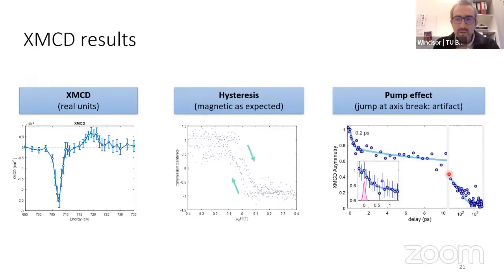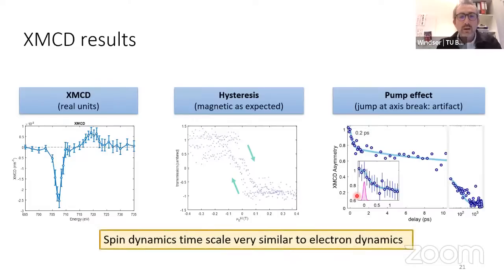I'm pointing this out because here there is a drop, and this drop here is artificial because in this part of the image, the resolution changes to be about 50 picoseconds because this is on much longer timescales. This is now in nanoseconds, hundreds of picoseconds, and this is in single picoseconds. And so we see that the initial drop here is on the order of 200 femtoseconds, which is very similar to what we saw in the electron dynamics, which is not so surprising. Metallic ferromagnets tend to have very fast spin dynamics. We also have a longer time scale here, which I'll come back to.